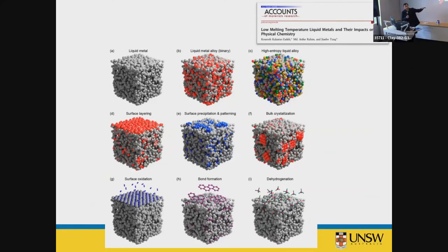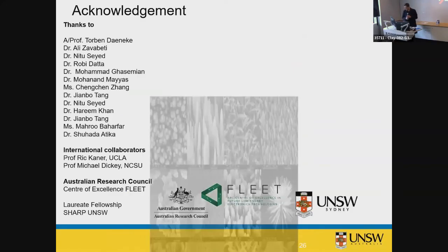Surface is layered. We can oxidize the surface, sulfurize the surface, harvest them. We can make things inside liquid metals, crystalline, think like crystallizing sugar and salt inside water. Here we're talking about crystallizing other metals into liquid metals and take them out. And it's a super catalytic material. Everything happens super fast. You can dehydrogenate organic material, make CC bonds, and you can use your imagination.